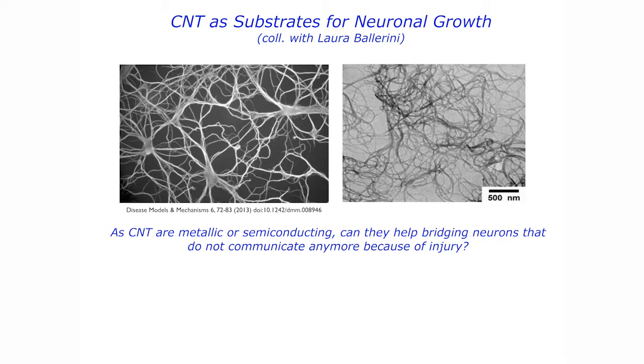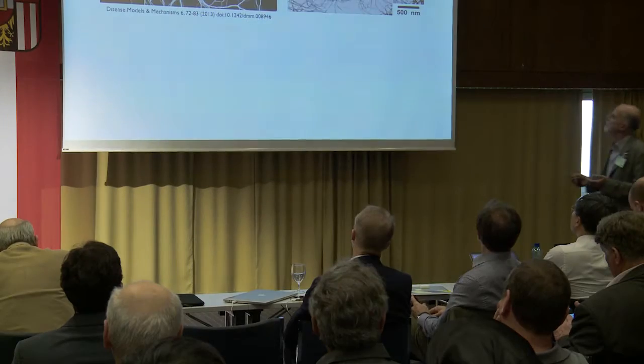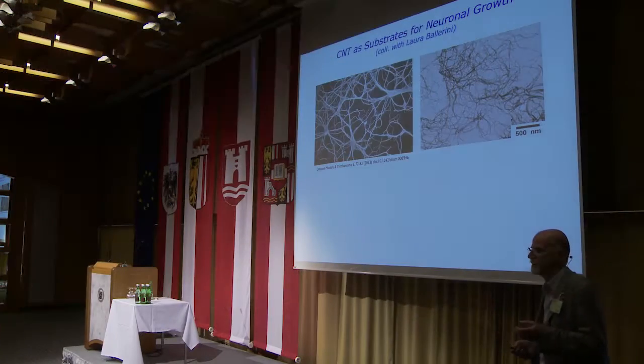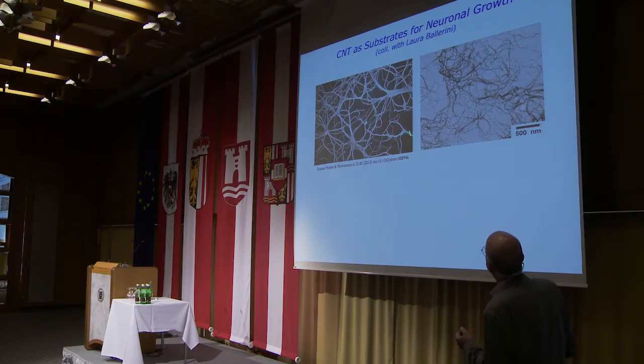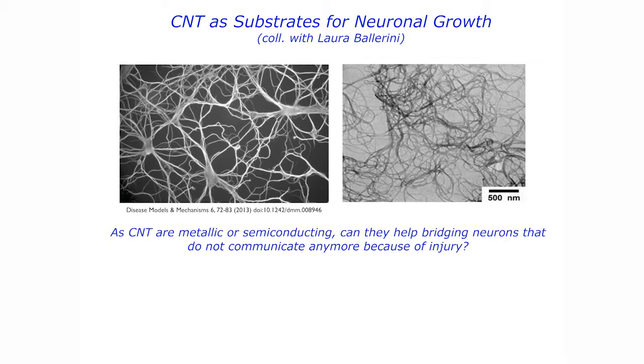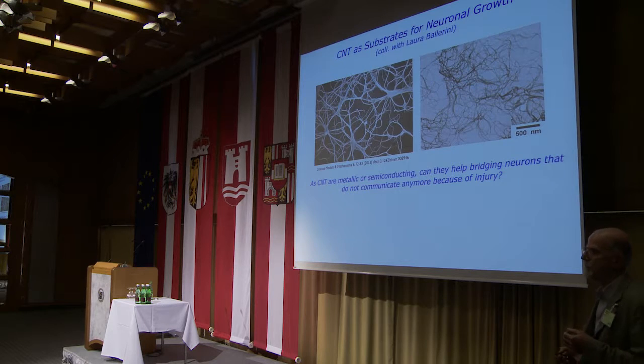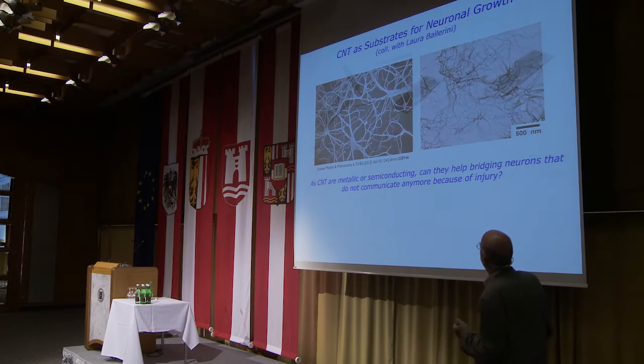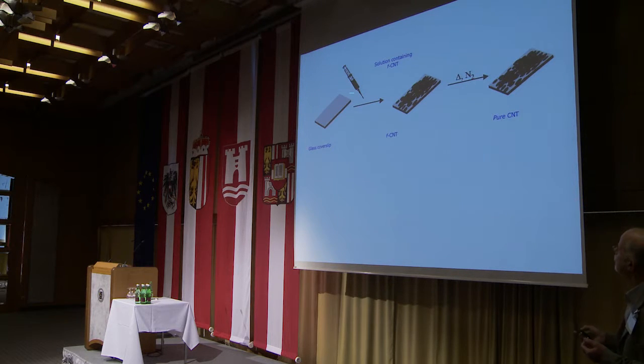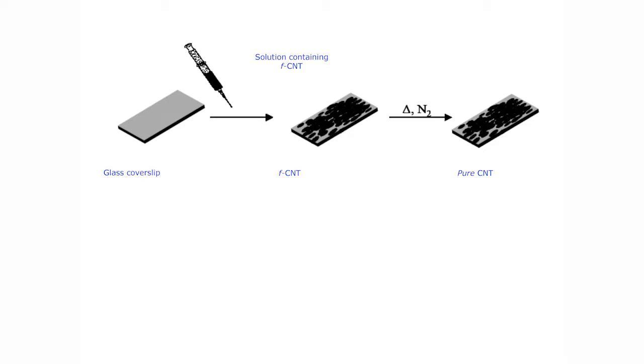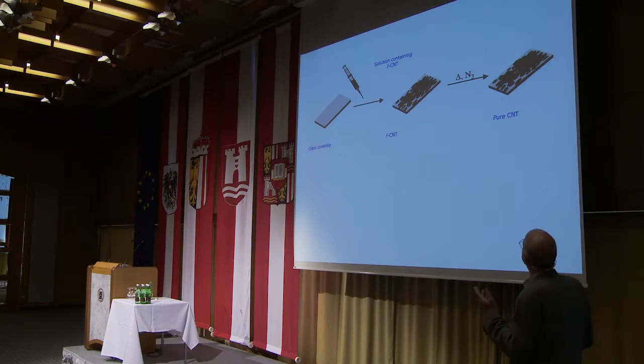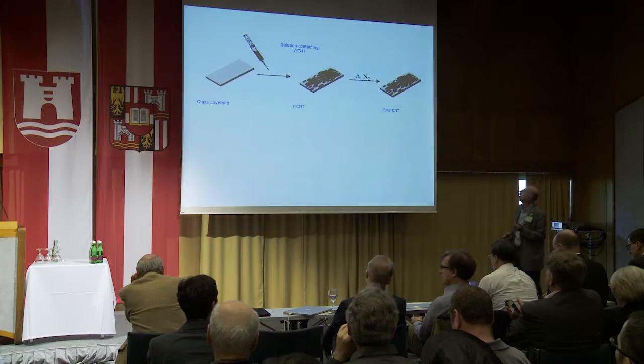From a morphological point of view, they are very similar, as you can see, even though the scale is different. I mean, neurites are much bigger in size than carbon nanotubes, but the shape is very similar. And so at a certain point, we decided, why should we not put in contact carbon nanotubes and neurons, so that we can see how communication between neurons is enhanced in the presence of carbon nanotubes. We started with a very simple approach in which we took a glass cover slip, covered it with functionalized carbon nanotubes, and then heated the functionalized carbon nanotubes in order to fix them on the surface of the glass.